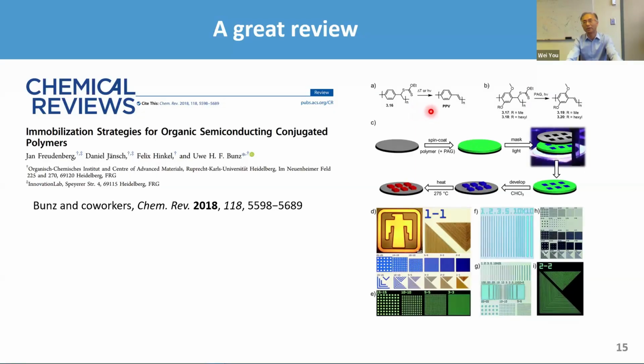This is how people made poly(phenylene vinylene) back in the days, a long time ago. You start with something non-conjugated. Because of non-conjugation, you have less pi interaction and rather flexible side chains, so you can make them soluble. That's why you don't need the long side chain in here. But now, if you add this very interesting solubilizing group, by using heat or light, you can remove it. You end up with a side chain free conjugated polymer.